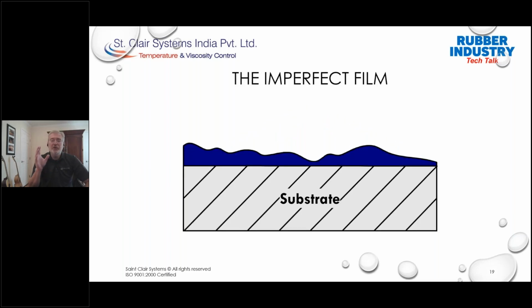Not only will the bond be stronger, but the layer will also be significantly stronger as well. But creating the perfect film requires perfect conditions. And more often than not, conditions are not perfect. As we've already seen, if the fluid temperature is wrong, it will affect atomization, spray pattern, flow out, etc. The result is an uneven film across the surface of the part, as we've demonstrated here.